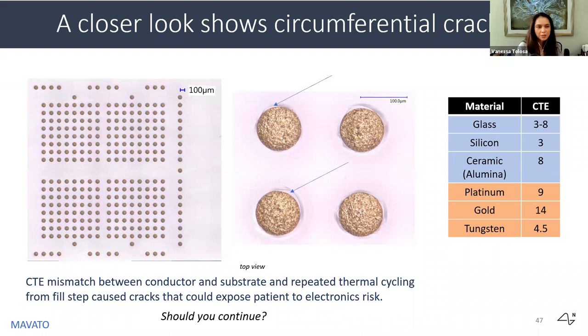And if you look at this table on the right, this is why for medical device implants, the conventional materials for feed-through substrates are ceramic and platinum. Because look at how well they're matched. It's like 8 and 9. Unfortunately, due to some of the issues I've discussed earlier around via holes and mechanical robustness, this particular combination of materials is currently limited to larger sizes and lower densities than what we need.